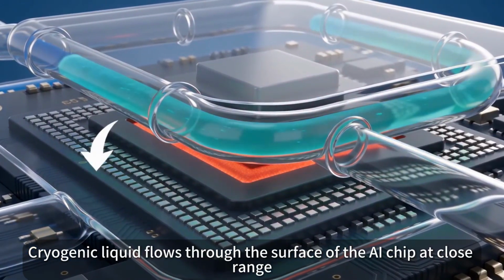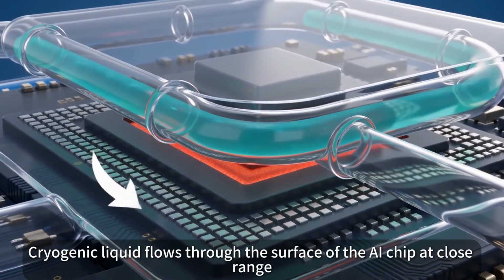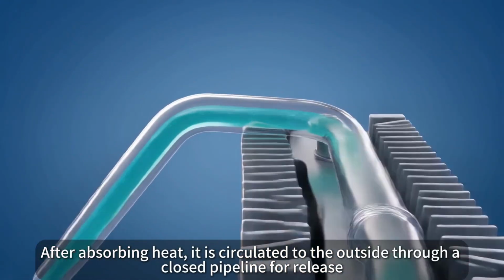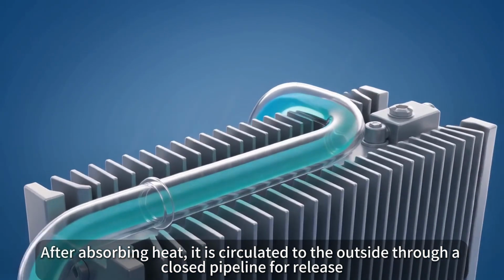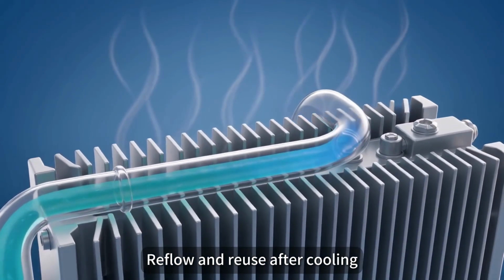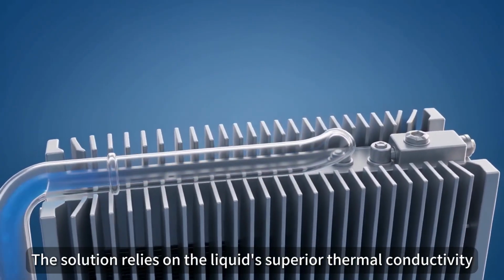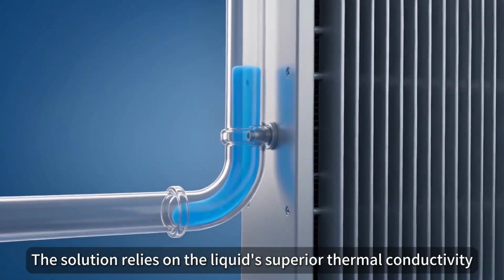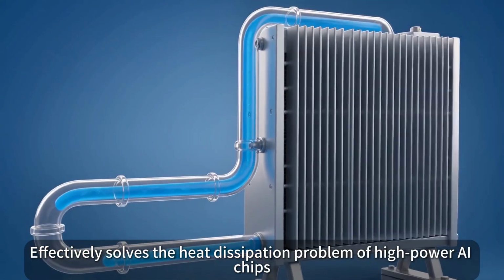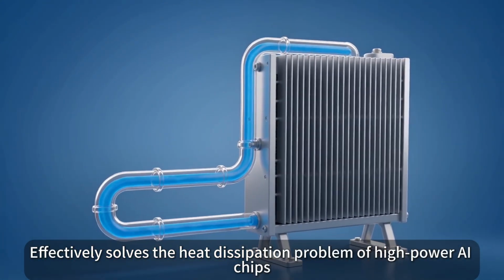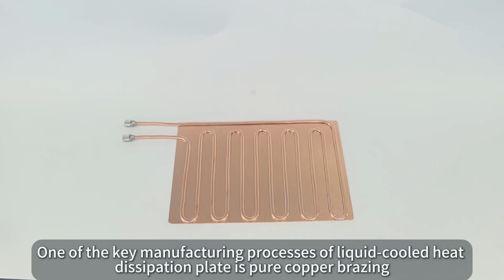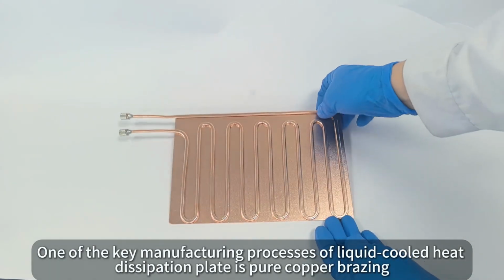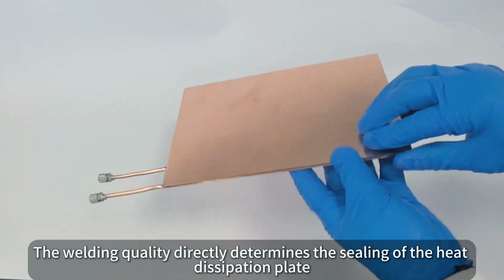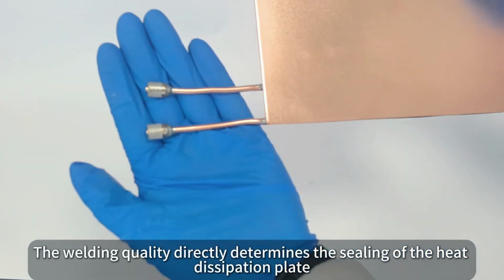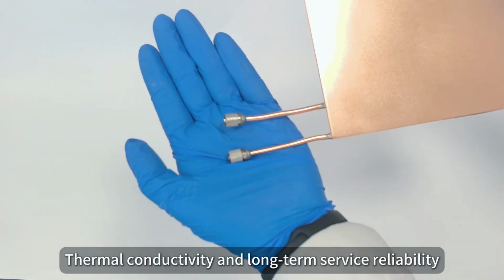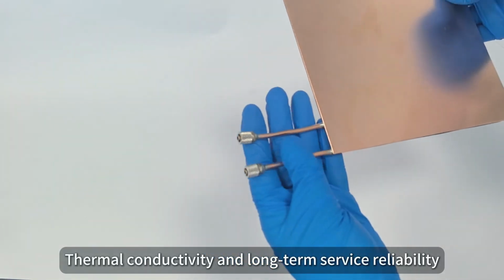Cryogenic liquid flows through the surface of the AI chip at close range. After absorbing heat, it is circulated to the outside through a closed pipeline for release, and reflows for reuse after cooling. The solution relies on the liquid's superior thermal conductivity, effectively solving the heat dissipation problem of high-power AI chips. One of the key manufacturing processes of the liquid-cooled heat dissipation plate is pure copper brazing. The welding quality directly determines the sealing, thermal conductivity, and long-term service reliability of the heat dissipation plate.